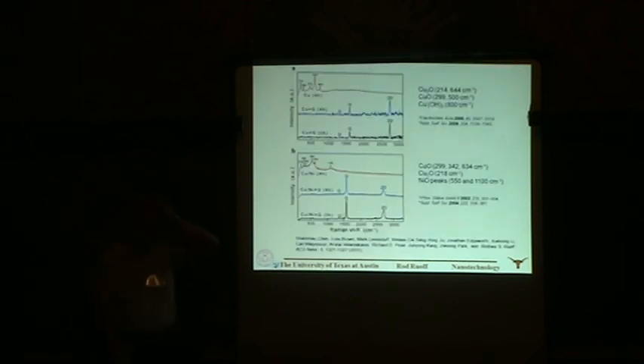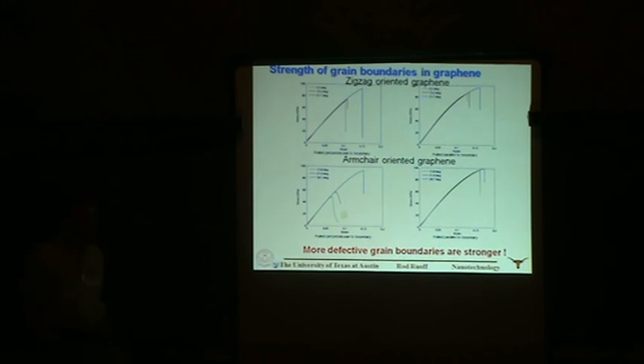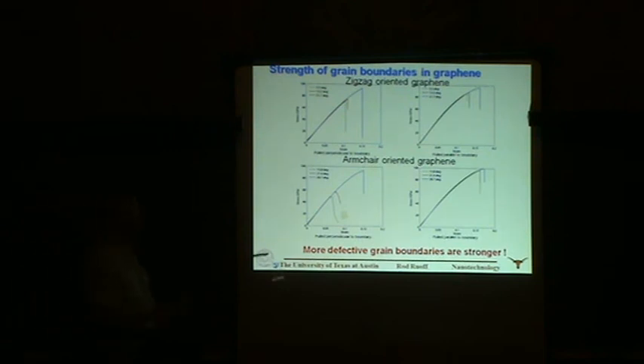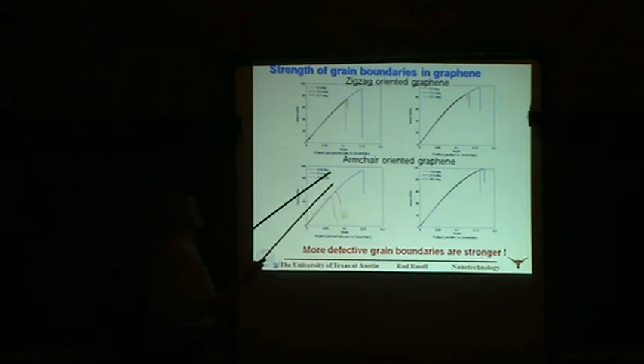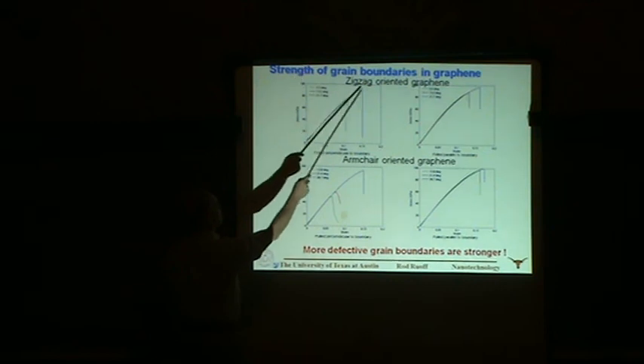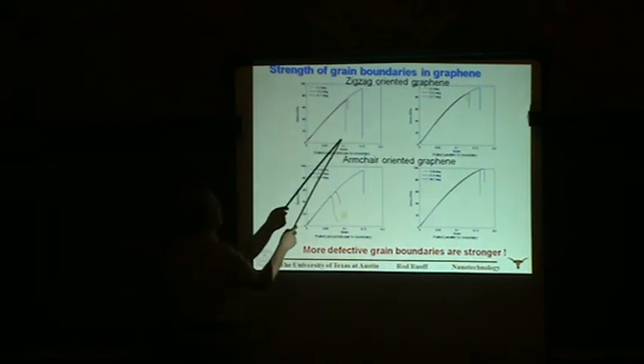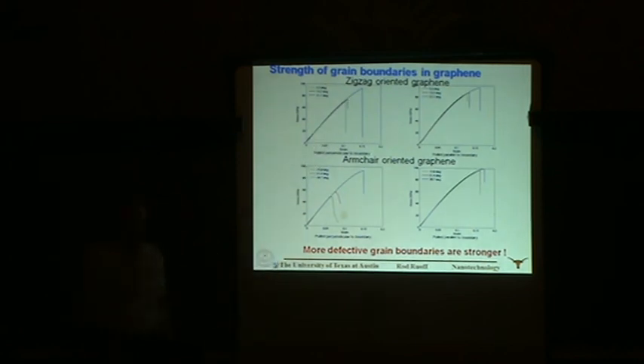Time for a couple of questions. When you talk about the grain boundaries, how much do they reduce the strength, given the theoretical strength is 130? To what extent? Yeah, so in this study, for example, I didn't show this study, so I'll show it now. At the different misorientation angles, you can see the drop from 130, which would be up here, down to the values shown at different strains, for example. And so the reduction is quite dramatic. Is this measured? This is purely modeled.